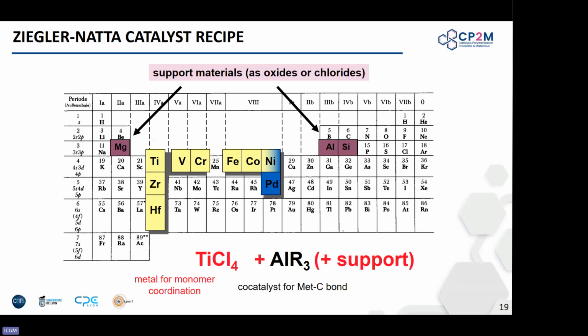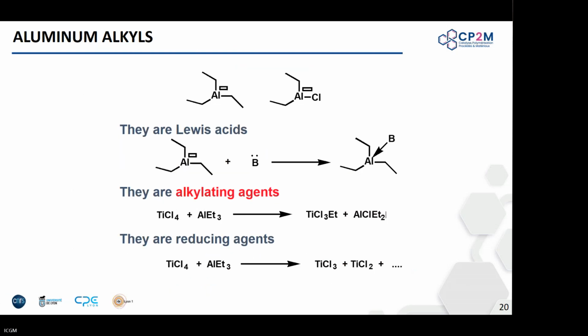Just for you, in a typical recipe for Ziegler-Natta, you'll probably have some TiCl4, a support, and some aluminum alkyls. Why aluminum alkyls? Because a pre-catalyst is usually titanium with a lot of chlorides. You'll need to make this metal carbon bond or metal hydrogen bond, so you will need to alkylate. You need a transmetallation, and you at least alkylate once. But you will realize that titanium 4 is not ideal, especially for supported catalysis, and it's usually a titanium 3 that is needed. So you need also something that can induce reduction, and these aluminum alkyls are also reducing agents. So these are two things that you need to remember.